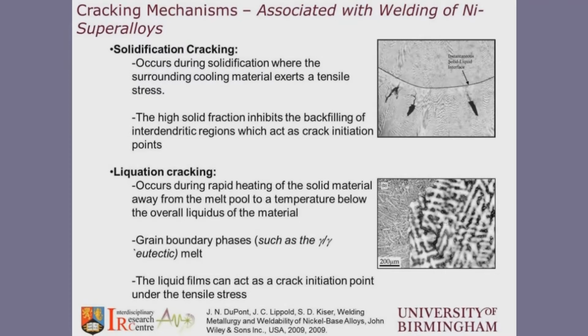...the formation of weak regions, which then, with the presence of tensile stresses during consolidation, during shrinkage, can inhibit the backfilling of the interdendritic regions, and as such will open up cracks, dendritic basically cracks, and will act as crack initiation points during solidification.